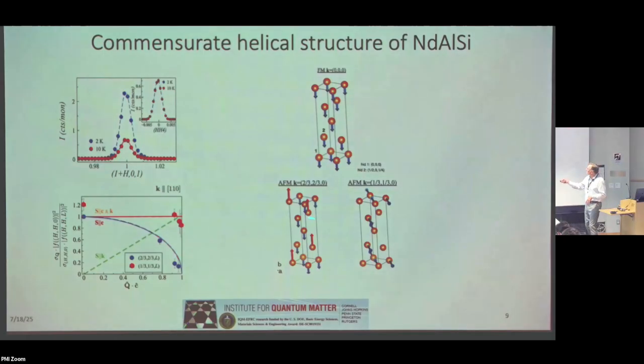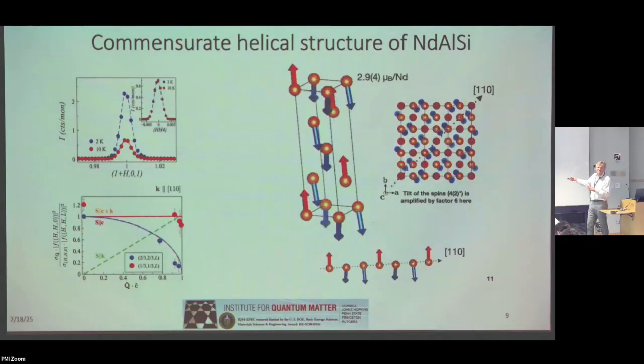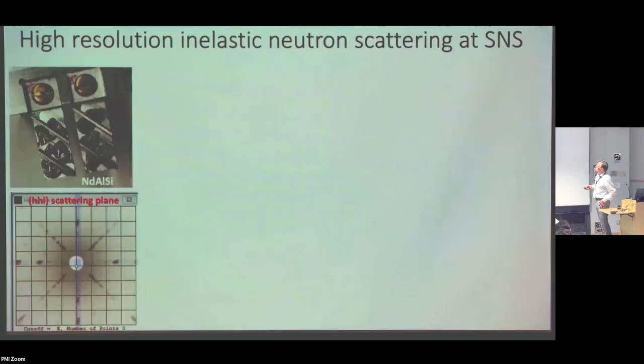We see it in momentum space, by the Bragg peaks. These are the three components. They get superimposed, and you get this kind of structure, which is predominantly what I've shown previously with the c-oriented spins. But the spins are kind of rocking back and forth, with this transverse component. That transverse component is driven by a DM interaction. And it's the component of the DM interaction which is perpendicular to the c-axis that's significant, because that's wanting the spins to actually develop an angle with respect to each other in the plane perpendicular to the d vector. So it gets to be quite a complicated structure, but we certainly do see that structure.